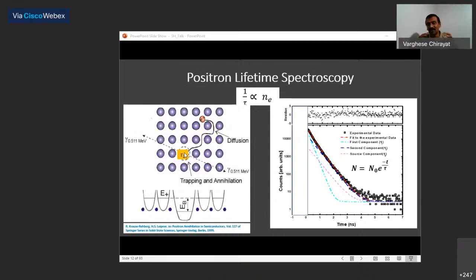So if your positron finds a defect and annihilates from there, it will have a very specific positron lifetime, because the positron lifetime, as I told you, is dependent on the electron density. And at the defect site, at the vacancy site, it is seeing a very specific electron density. Now, if it annihilated somewhere else, say for example in the interstitial position, just to define, the interstitial position is the position in between the ion cores. If it annihilates at the interstitial position, it sees a completely different electron density. It actually sees more local electron density than it will see in a defect site. And that will give you another lifetime, which I've shown here as tau1 and tau2.